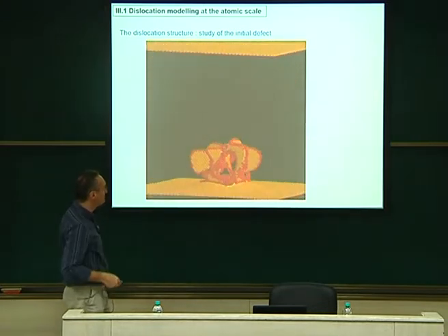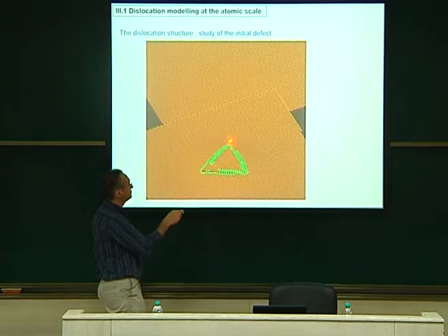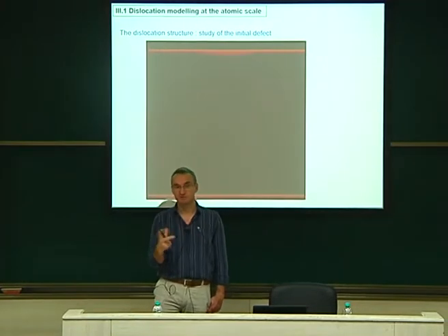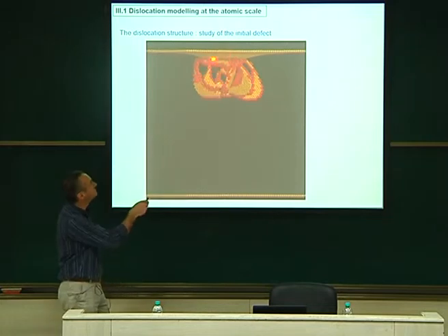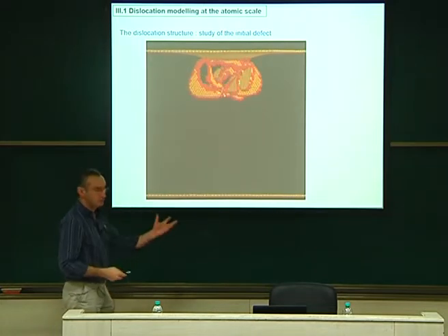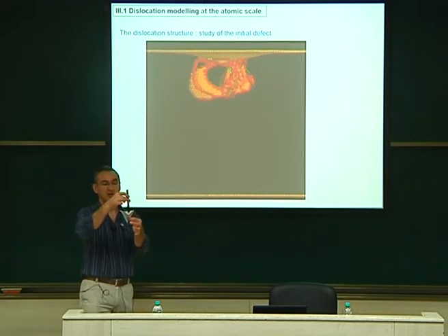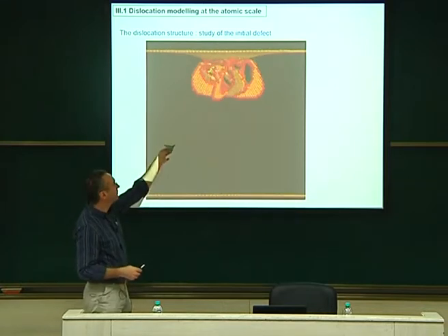And at the surface, this plots a triangular shape like this. The triangular shape corresponds to the crystal symmetry. This is imposed by the symmetry. Although I had a sphere, the intersection with the surface is triangular. Okay, and you can use a Thompson tetrahedron. Remember that this was the 1 1 1 surface, so I'm like that, and this fits well with the threefold symmetry of the 1 1 1 orientation.